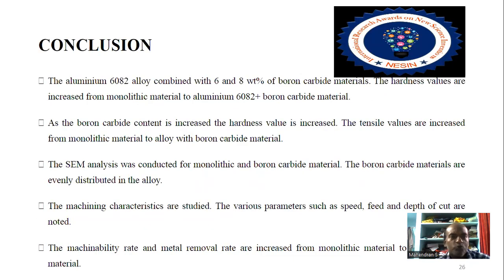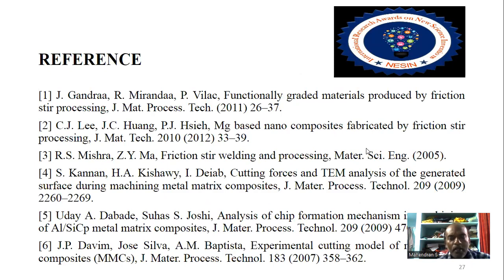These are the final conclusions. Final conclusion says, compared to monolithic material, this composite material, especially boron carbide composite material, has more hardness value, more tensile value, very good SEM images, evenly distributed SEM images, and very good machinability rate under such parameters. Feed rate and machinability rate are also improved.